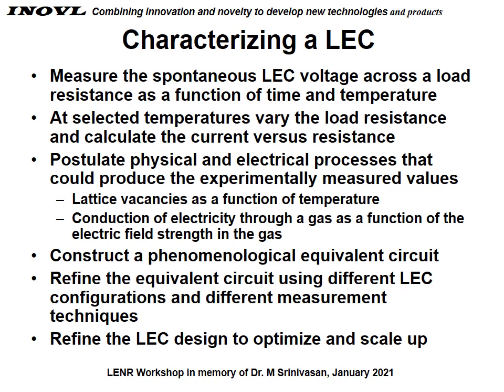Characterizing the LEC involves measuring the spontaneous LEC voltage across the load and resistance as a function of both time and temperature. At selected temperatures, vary the load resistance and calculate the current versus resistance. We postulated physical and electrical processes that could produce the experimentally measured values, and again, this is where studying the work of Thomson and others was important.